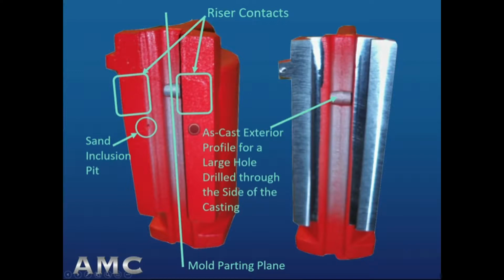If a riser contact is underground, the grinding may cause the machine surface to not clean up. On the other hand, if the contact is left too high, especially in alloys that are more difficult to machine, such as steel, a sudden heavy cut may damage the tooling.